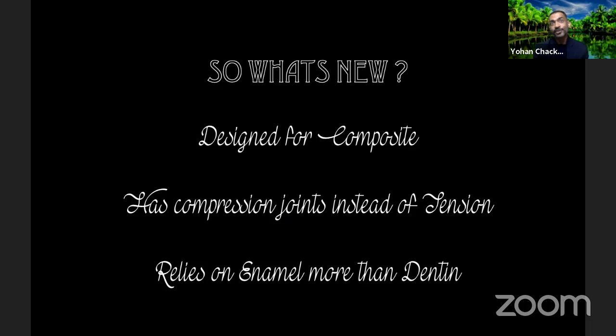So we should not be complicating the matter by relying on dentine bonding, because the truth of the matter is dentine bonding is unreliable. The bond strengths that you get on day one, if you compare the same bond strengths on day 30, day 60, day 90, you will find a gradual deterioration. And after about 6 months or so, the dentine bond strength is about, what, 40 to 50% of the original bond strength. That is not a reliable substrate to bond to. You cannot rely on dentine, and you should not.